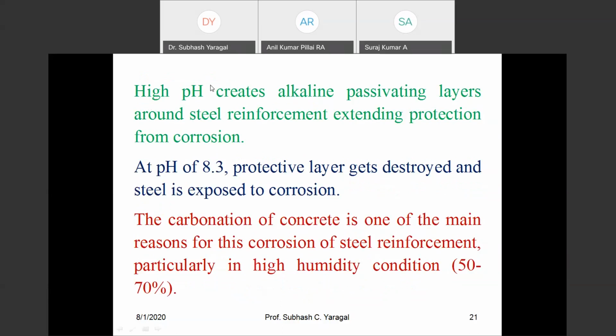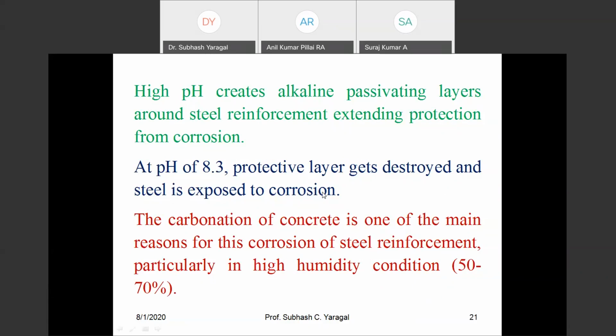Now, this matters for us because a high pH creates highly alkaline passivating layers around the steel reinforcement, protecting it from corrosion. The more the alkalinity, the more your reinforcement is protected. Now, what happens at a pH of 8.3? The protective layers get destroyed and steel is exposed to corrosion. The carbonation of concrete is one of the major reasons for corrosion of steel reinforcement, particularly in high humid conditions in coastal regions, where humidity can be anywhere from 50 to 70%. Places like Mangalore have 90 plus humidity. In such cases, carbonation of concrete is a serious threat for the deterioration of concrete.